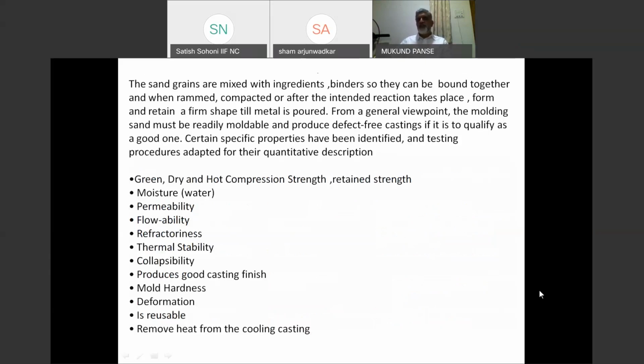The grains are mixed with ingredients, binders, so that they can be bound together when rammed, compacted or heated. And the formed mold should retain its shape. From a general viewpoint, the sand should be readily moldable and should not produce defective castings if it is used. Certain specific properties have been identified: green, dry, hot compression and retained strength of a sand mixture.